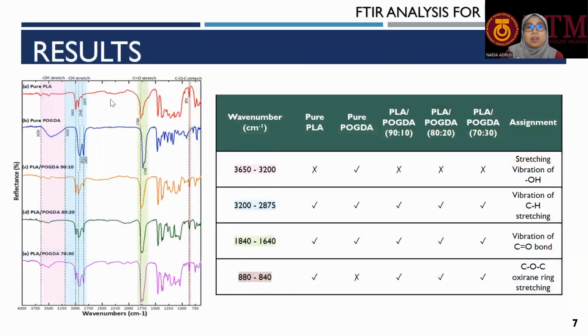So here are the results of the FTIR showing pure PLA, pure POGDA. Pure PLA is the first spectrum, pure POGDA is the second spectrum, and then the blends of PLA POGDA of 90-10, PLA POGDA of 80-20, and also PLA POGDA of 70-30. Here we can see the assignment for hydroxyl group, alkyl group, and also C double bond O and oxygen ring stretching. So from here, we can see that when we have the blend, we can see the peak assignment for both compositions, PLA as well as POGDA.